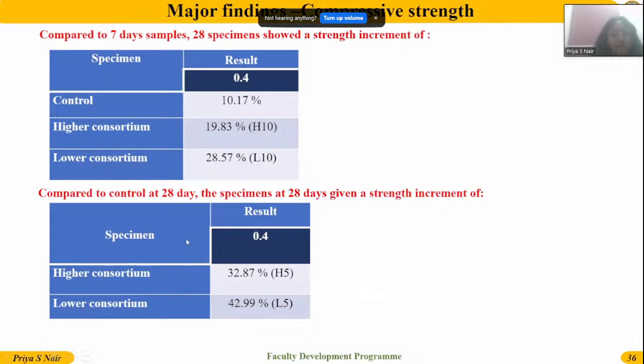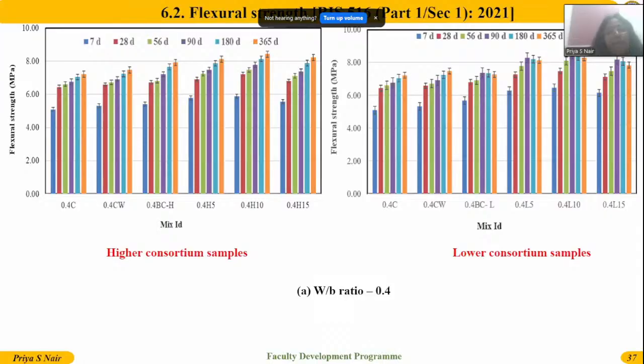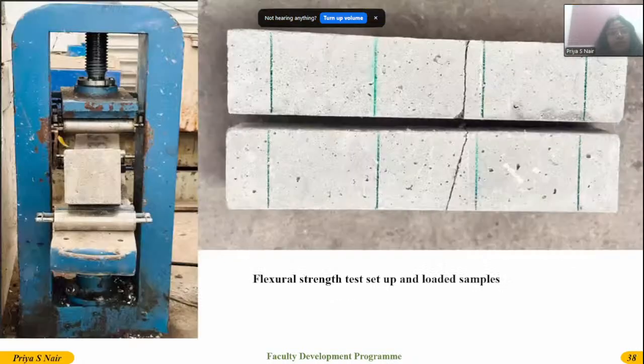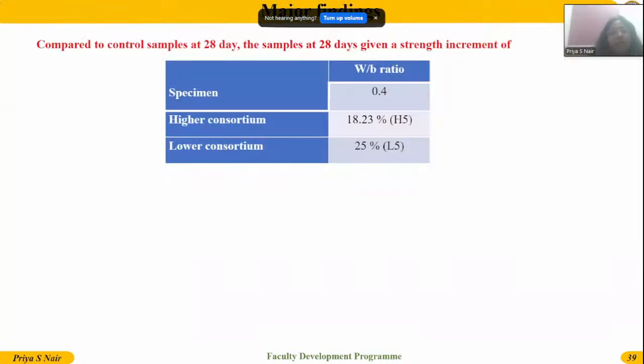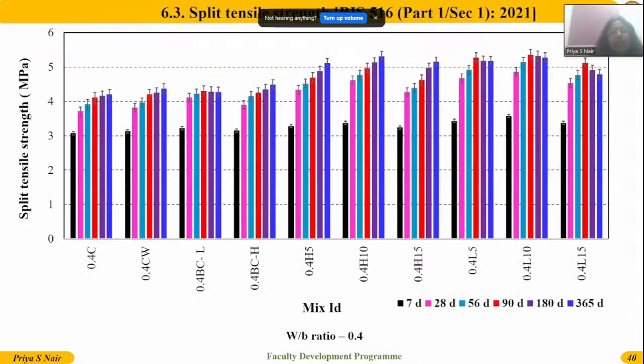So it was seen that compared to the control at 28 days, the specimen at 28 days gave a strength increment of 42.99%, approximately 43%, in the case of lower consortium, and for higher consortium, it was 32.87%. So lower consortium has given the maximum result at 28 days. Only I added the 28 days result. The same trend happens in the case of flexural strength also. In the flexural, this is the figure, and lower consortium has given a maximum result of 25% and higher consortium 18.23%. So this is the split tensile strength. The same scenario happened there also.